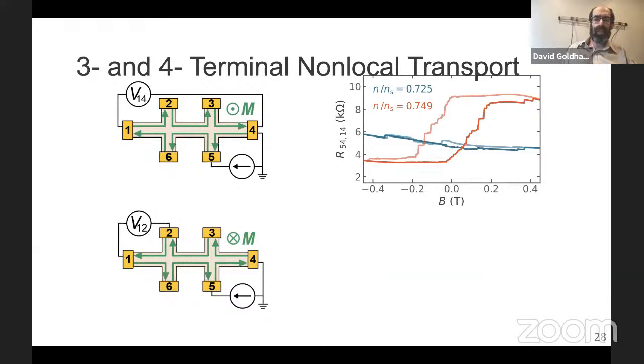In the interest of time, I'm not going to go through this in detail, but I'd be happy to answer questions. There are typical kinds of measurements that people measuring quantum Hall like to make to diagnose whether there's non-local transport. There are 3-terminal measurements and 4-terminal measurements. And what you can see here in such a 3-terminal measurement is a large signal that's hysteretic if you're sitting right at 3/4 filling of the band, 3 electrons per moire. If you go even a little bit away, just a few percent away in filling, that signal goes away.